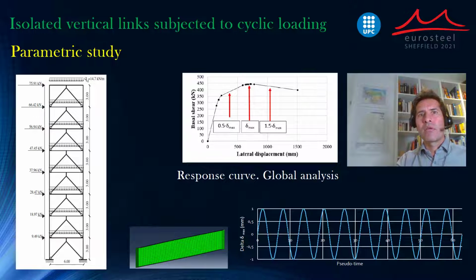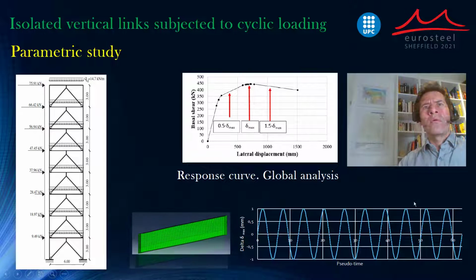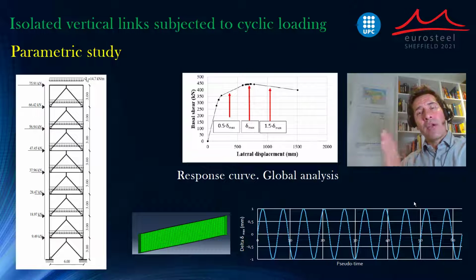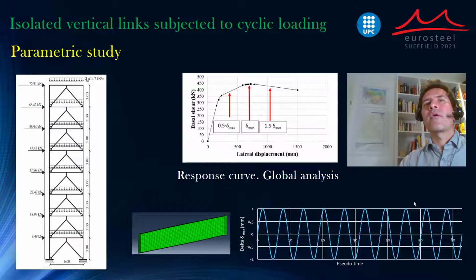For understanding this parametric study, we need to understand that first of all we develop a global system pushover analysis, we obtain the response curve, and in this response curve for different configurations we detect 3 levels of loading. In the global analysis we detect the maximum load, which generates a certain displacement delta max. We divide this displacement by 2, obtaining 0.5 delta max, and we multiply this displacement by 1.5, obtaining another, higher displacement on this response curve.